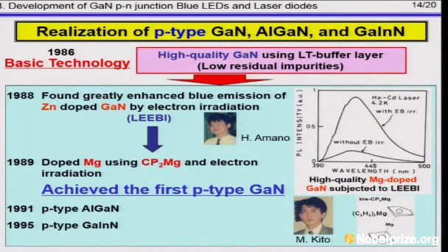In early 1989, Masahiro Kito carried out the magnesium doping of high-quality gallium nitride crystal using bis-cyclopentadienyl magnesium, then applied the low-energy electron beam irradiation to the sample and found that the magnesium-related blue luminescent intensity had been markedly enhanced, while the spectrum shape remained unchanged, and that the sample had been converted to a p-type crystal.